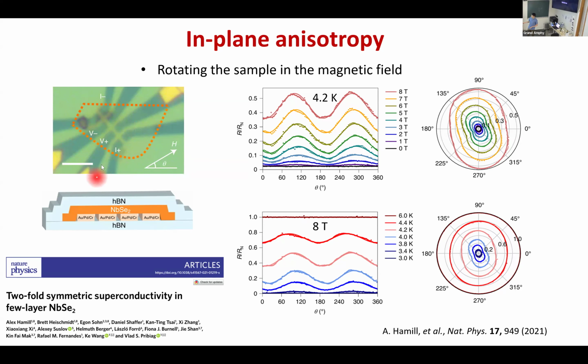This group did two things. First, they measured the resistance, and the upper critical field, not just sitting around the superconducting transition. This sample starts to show a superconducting transition around 4K, and reaches zero around 3K. In between this range, you have the superconducting transition going down, but when you rotate the magnetic field at about 8 Tesla, the resistance response is anisotropic. And when you plot this in polar coordinates, it looks like a twofold, peanut-like structure.